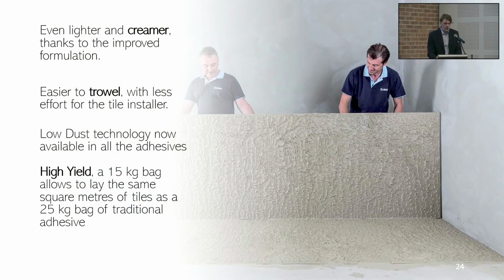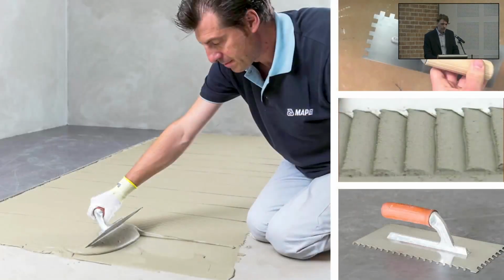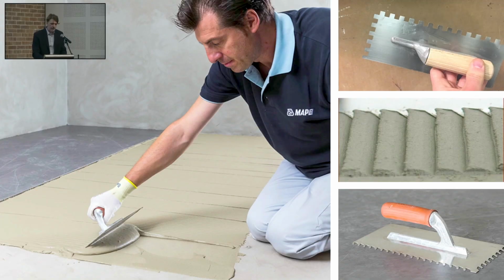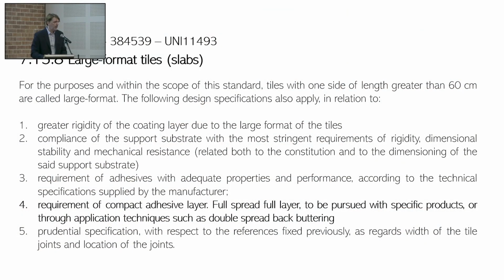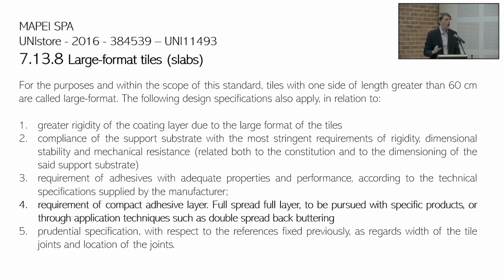And, okay, of course, just to finish this part, we need to consider the way we apply the adhesive. So it's not enough to adopt the right system, we also need to fix them in a proper way, because the application of the adhesive can really affect the final result. In Italy, for example, we have some local norms. They say when you apply a tile with one size larger or equal to 60 centimeter, you need to take the tile, apply the adhesive on the back, apply the adhesive on the floor or on the wall, and fix them together, just to try to cover they say 95% of the back of the tiles.